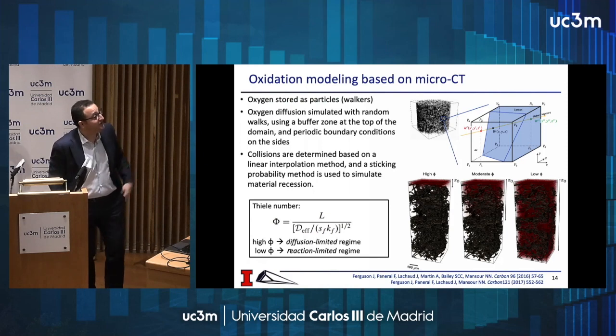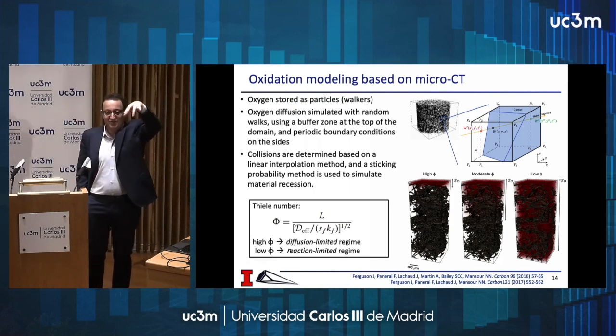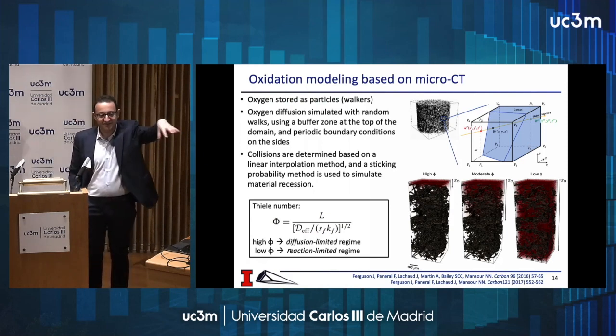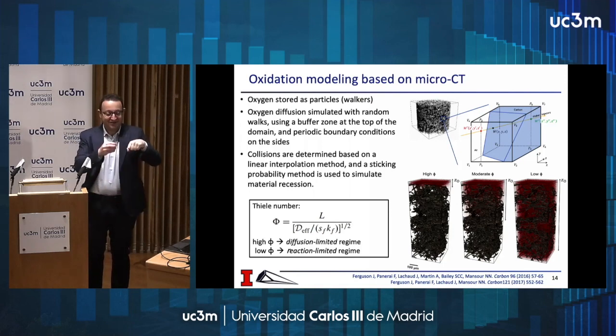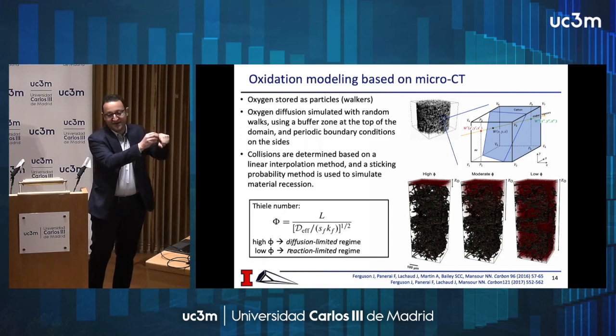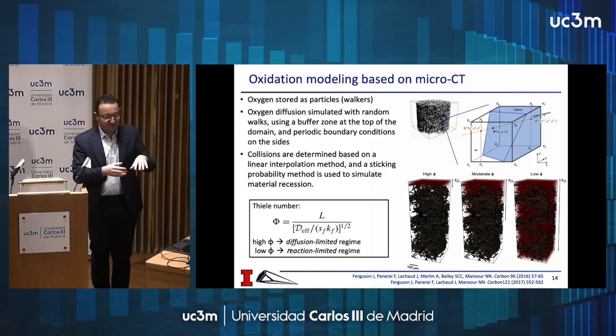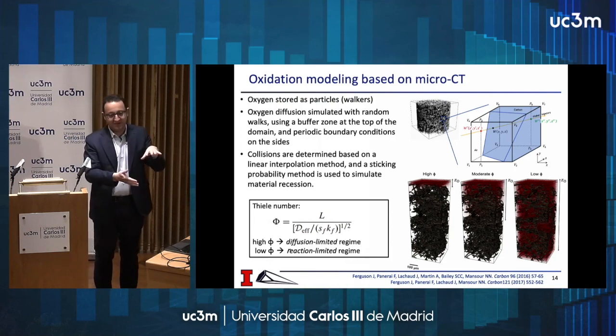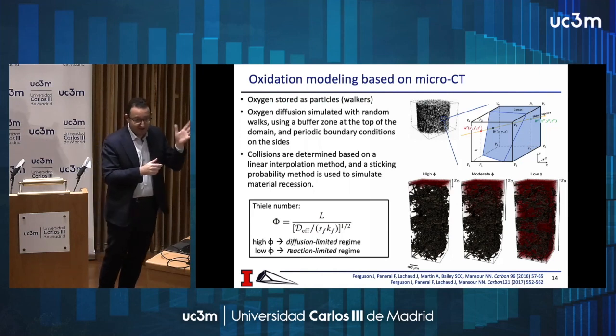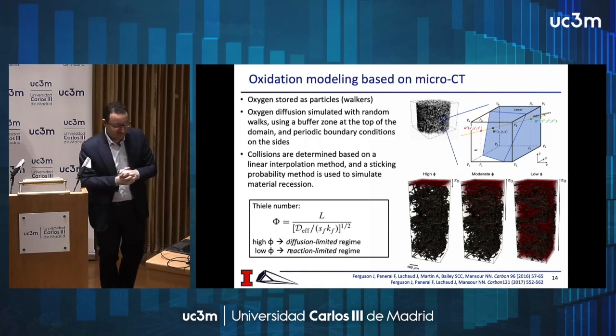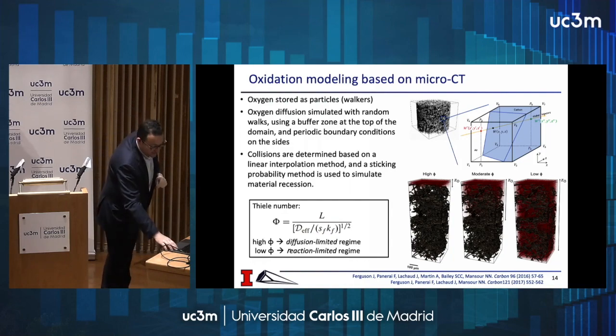So what we do is we take a three-dimensional image. We walk particles inside the porous medium, particles that represent oxygen. These particles hit the fibers and take some of the material away. So we simulate diffusion with random walks, and we have a sticking probability model to simulate the removal of carbon. I can give you further details later on if you're interested.